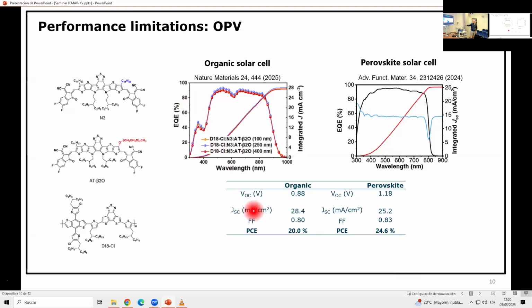And this is reflected in, so power conversion efficiency is not only current, because if you want power out, it means you need current and voltage. And the power out is current times voltage. So getting current, getting photons converted to electrons, you need it, but it's not enough. You also need voltage. And that's what you see here, and it's basically the voltage you have at open circuit. For this one, it's 0.88, and for this perovskite, it's 1.18.